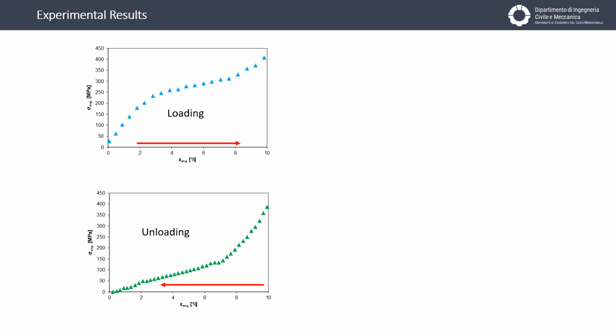Tests have been performed by using a loading and unloading cycle test, and here we can see the first cycle split in two different cases. The first one is the loading condition, with the presence of the first stage characterized by the presence of austenite. The second stage is the plateau, but you can see the plateau is not characterized by a slope equal to 0, but the slope is greater than 0.